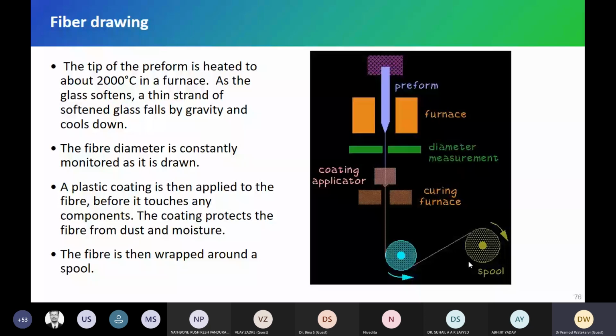Its diameter becomes 250 micrometers. So 125 becomes 250 if you take coating plus glass fiber, but glass is only 125 micron. In that glass, there is a core which is only 10 micron. So those are the dimensions: 10 micron over 125 micron diameter. Then over that there is plastic, which, if you take the total, is 250 micron total diameter.